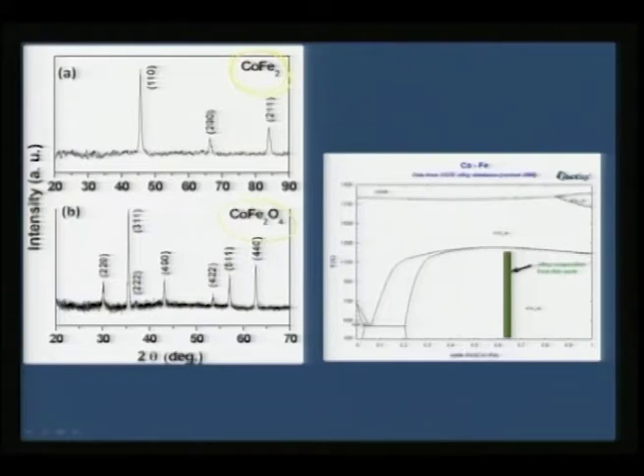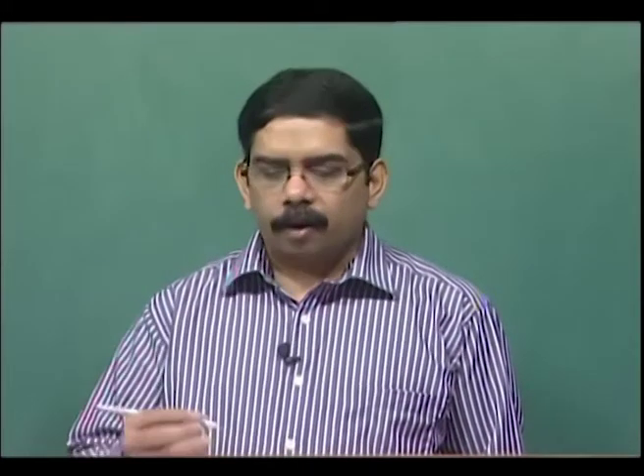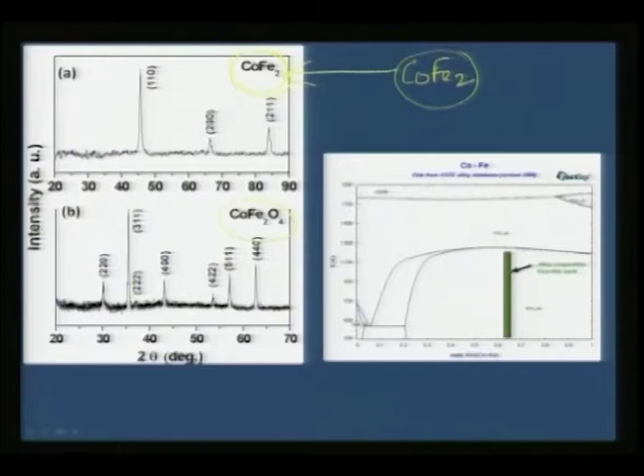So, if you carefully look at this pattern, this amounts to CoFe2, which is a ferromagnetic alloy, and in the literature there is no way that you can make this alloy using a wet chemistry route. You would always end up with an oxide, and the only way that you can prepare such an alloy is by conventional metallurgical route, where you can use a crystal growth method or so to grow a CoFe2 alloy, but it has never been reported in the wet chemistry approaches to isolate a cobalt Fe2 alloy of this form with a clear single phase. What is the advantage?